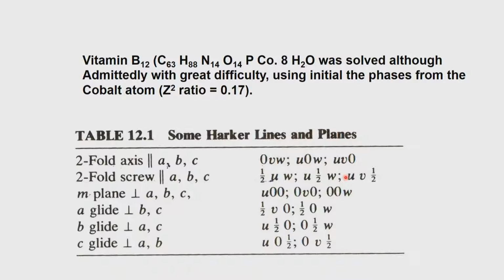So, if the space group is P212121, and we compute the Patterson, we know it is P 2/m 2/m 2/m, but the three projections associated with the x, y and z directions, which are parallel to A, B and C, will tell us about the possibility of locating the heavy atom positions to start with, and secondly it will also tell us what is the possible translational component associated with that particular symmetry operation.